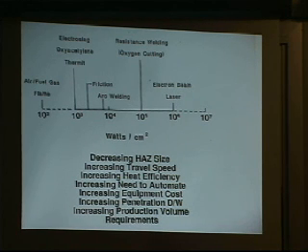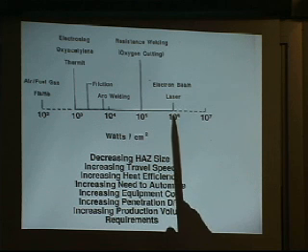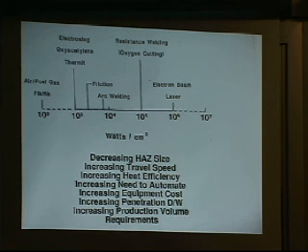It turns out if you, instead of using a 100,000 volt electron beam, you use a 2 or 3 million volt electron beam, you can overcome that surface heating because the electrons have enough energy that they are deposited a millimeter or two deep beneath the surface. And so you don't get just this straight surface heating. You are actually heating a volume of several millimeters, depending on how many million electron volts you get.